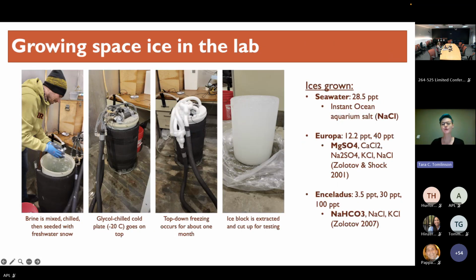Because obviously we're not going out to these moons to collect samples yet. Instead, we make our own down in the ice lab. So we mix up whatever ocean we need in our big Nalgene bucket, put a cold plate on top, set it to -20, wait for about a month, insulate the sides so that we can guarantee that directional freezing that we want, the top-down freezing. That's what gives us the crystal structure that we think best mimics what we would expect to find on the icy moons. So it's the same way that ice freezes, like I said, from the top down on the ocean. So after between 4 and 6 weeks, we extract our ice block, cut it up for testing. And these ice blocks are usually about 33 centimeters across, between 30 and 50 centimeters thick. So we are working on decently sized scales here.